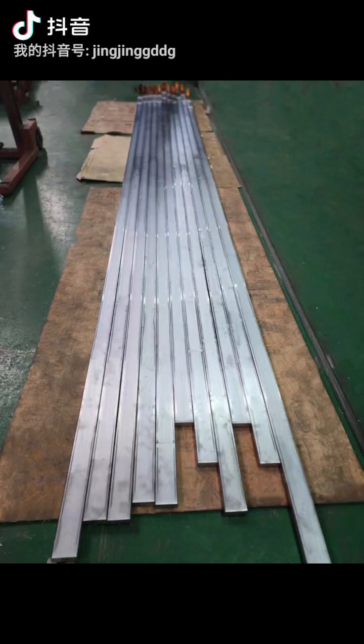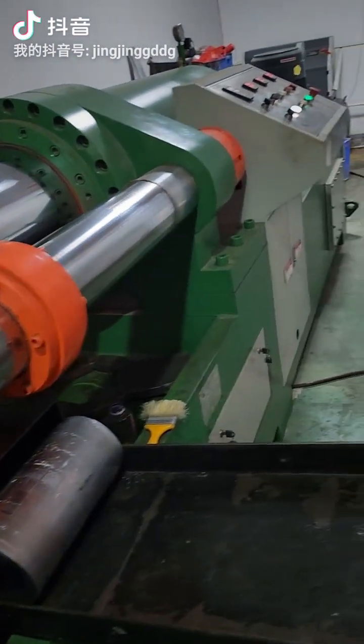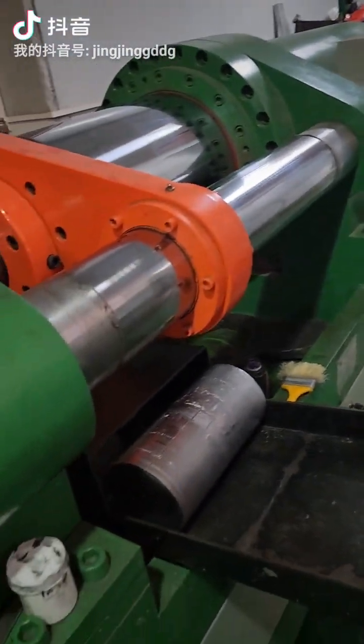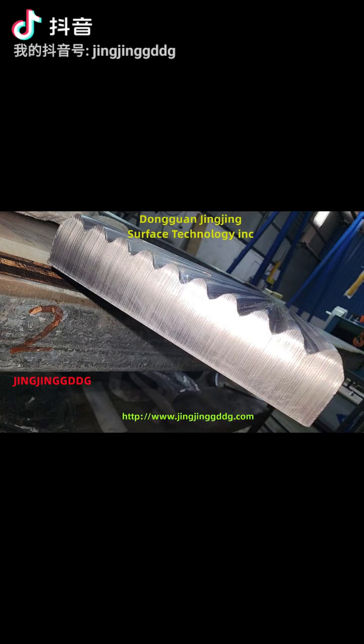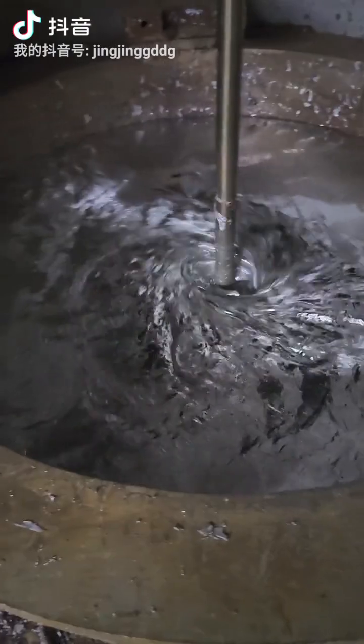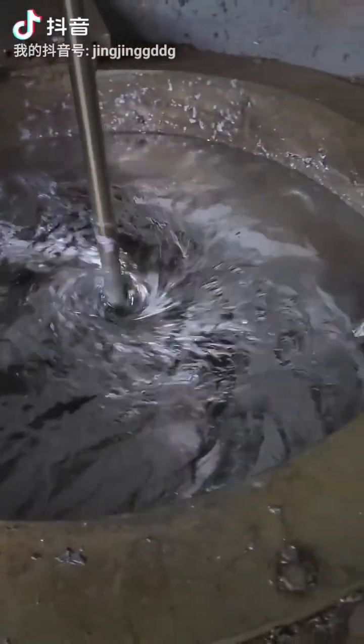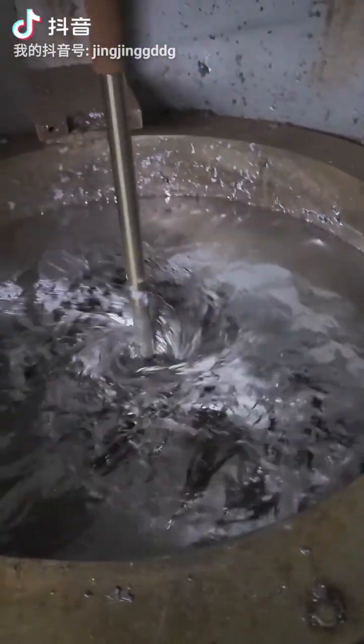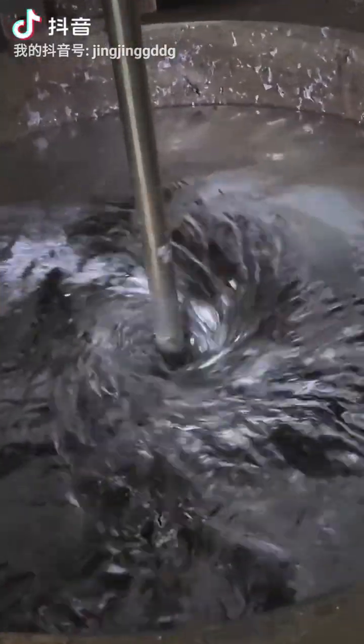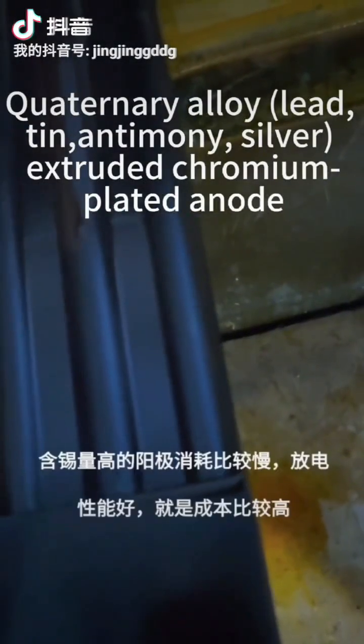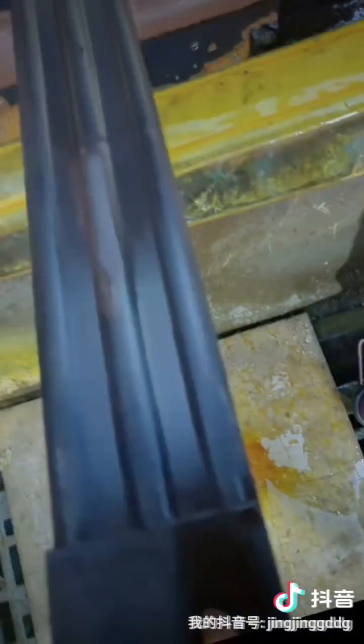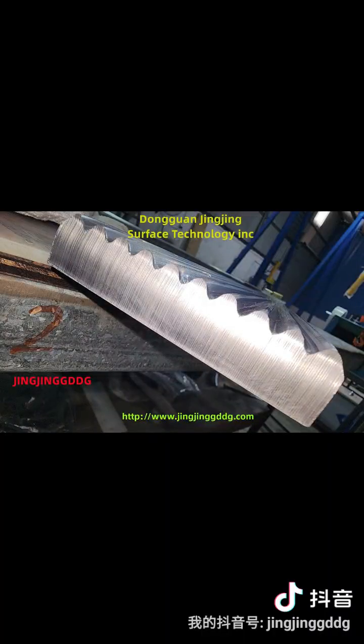Third generation, after summarizing years of experience, we use high-density extrusion molding technology, 1,000-ton extruder extrusion, for chrome-plated anodes. By using high-quality lead tin raw materials, purity greater than or equal to 99.9%, adjusting the proportion of lead tin content 3 to 10%, antimony content 2-5%, and silver content 0.5-1%, and optimizing the structure of the anode, and using high-pressure extrusion molding technology.